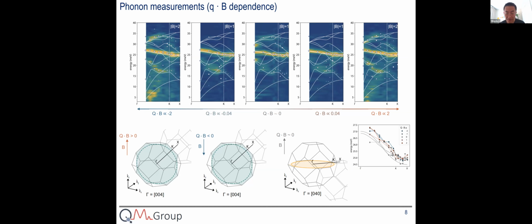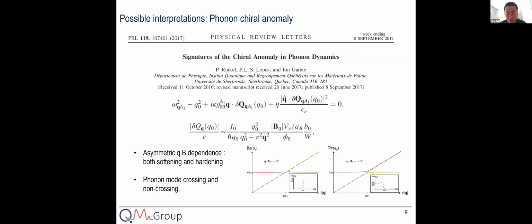The other thing is that there are very different splittings. Along certain Q points, there is very little effect on the field-induced phonon energy change, but along some other directions the change can be really large, about 1.5 milli-electron volts. So what we were trying to do is actually giving pretty good agreement, especially since we need only one fitting parameter here, is to link all this to the possible phonon chiral anomaly.